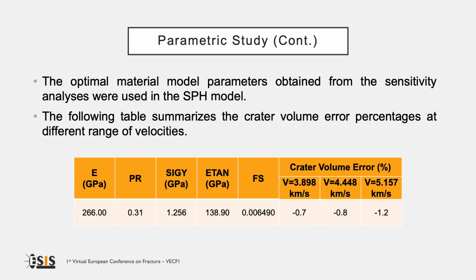The results of the parametric study are finally summarized in this slide. The best set of input parameters is obtained by keeping the baseline values of the elastic modulus, the Poisson ratio, the yield strength, and the tangent modulus, and by increasing the value of the failure strain by 10%. This set of parameters leads to a very low error on the crater volume. This error is below 1% for all the impact velocities except for the highest one, where it is 1.2%. The variation of the error between the worst and the best configuration is 0.5%.